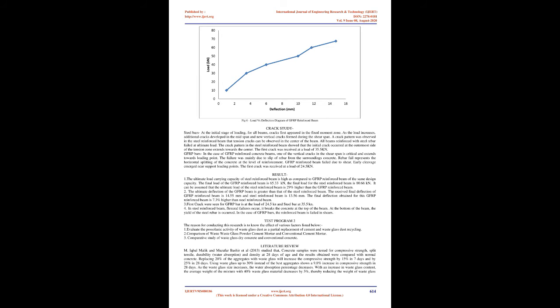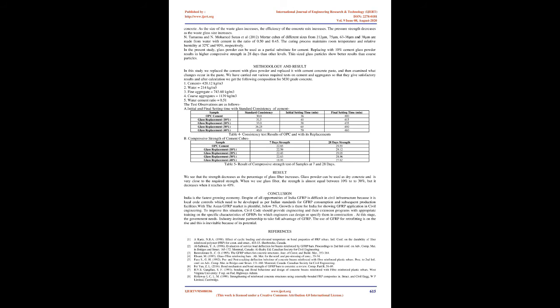3. First cracks were seen for the GFRP bar at a load of 24.5 kN and for the steel bar at 35.5 kN. 4. In the steel reinforced beam, flexural failure occurs, breaking the concrete at the top of the beam. At the bottom of the beam, yielding of the steel rebar occurs. In the case of GFRP bars, the reinforced beam fails in shear.